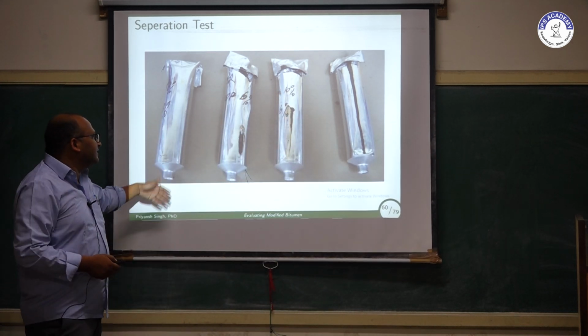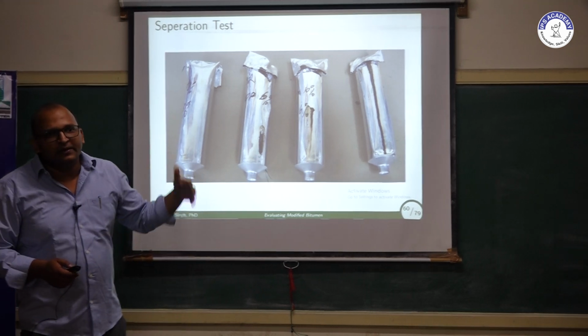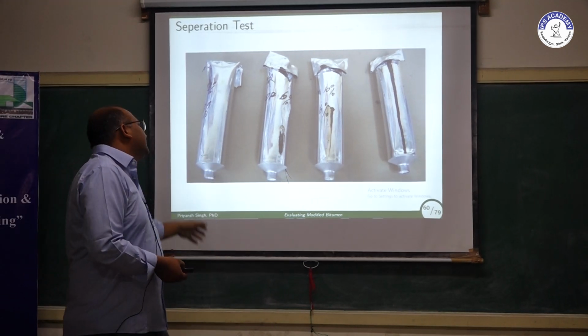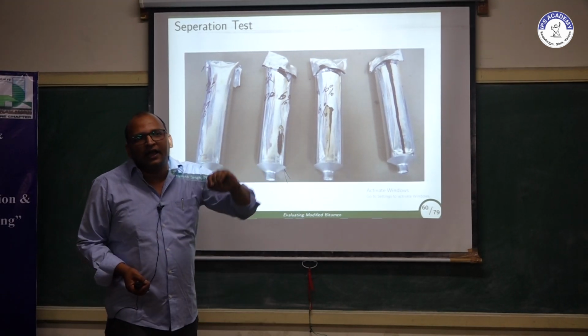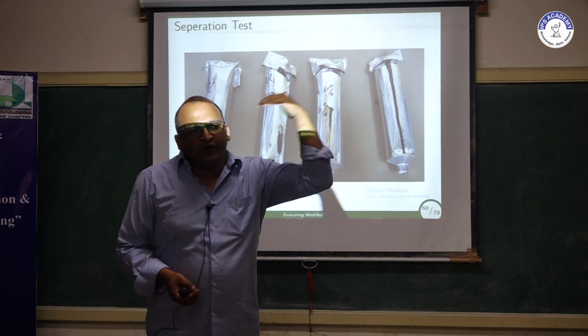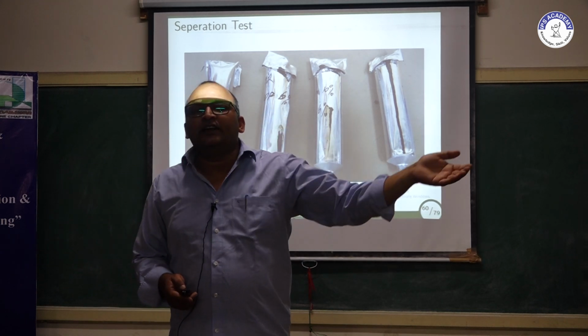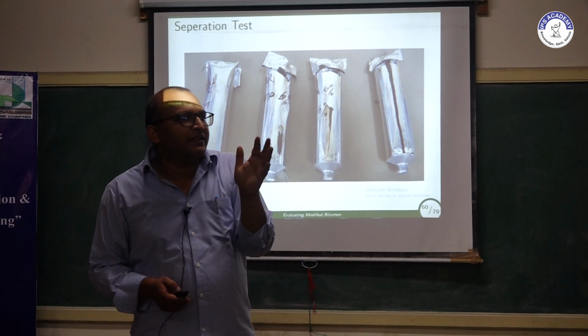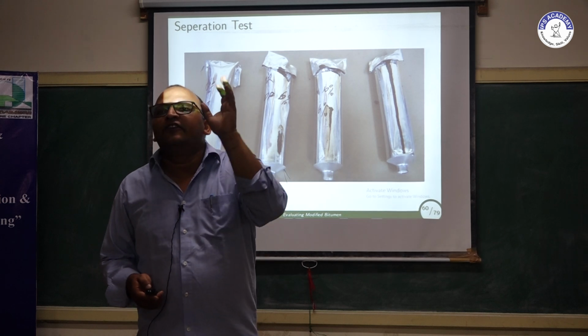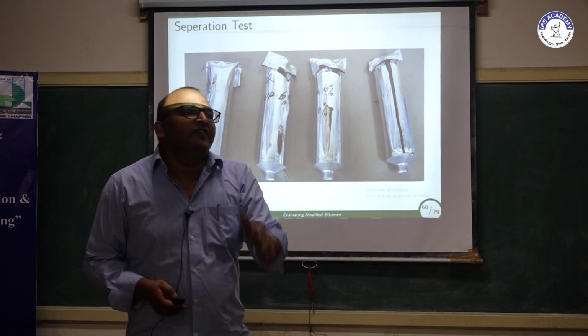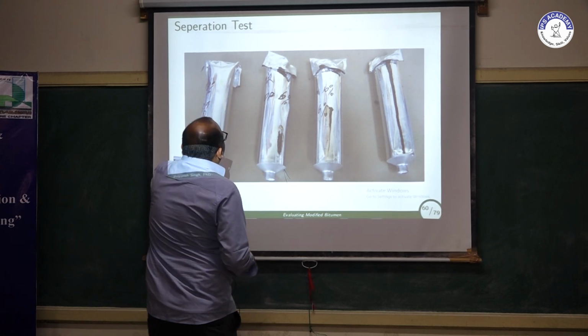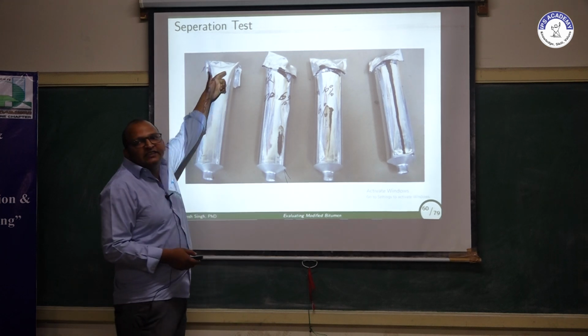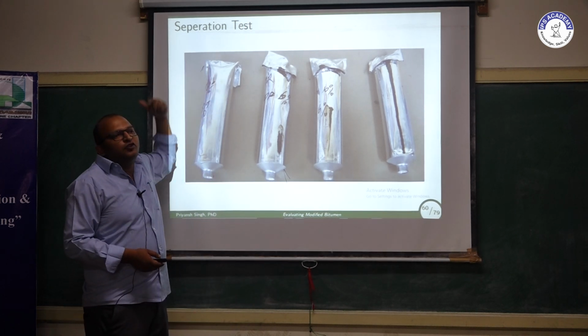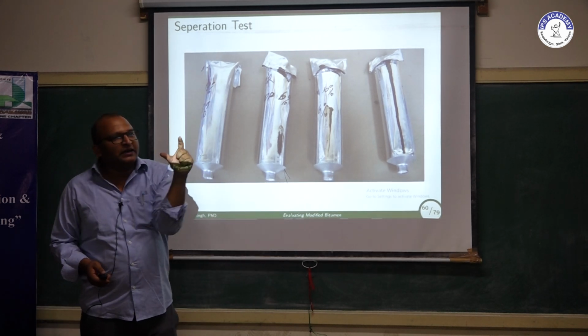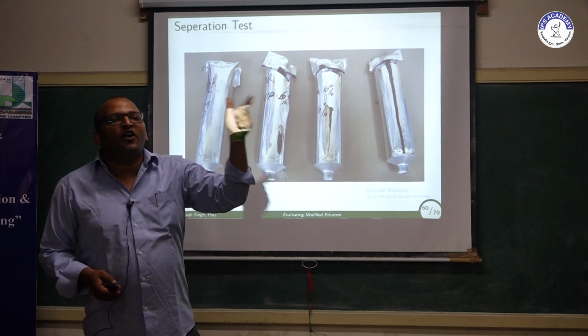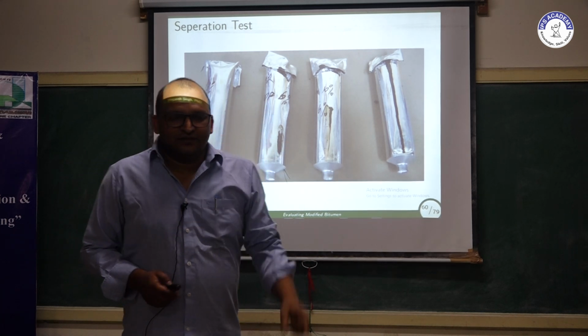In order to characterize that, there is a stability test. In the stability test, we will put our binder inside these types of aluminum tubes, and then keep them for 24 hours at elevated temperature, and after that 24 hours at freezing temperature. Then we will cut the bottom part and the top part, and check the properties of the top and bottom. The properties of top and bottom should not differ too much.